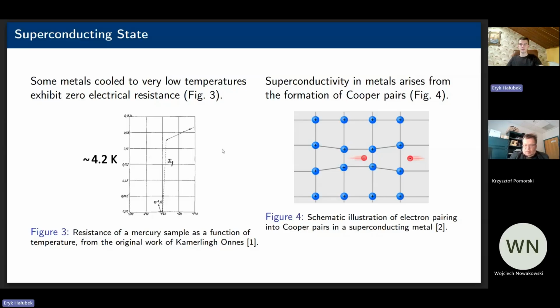So now we know that the critical temperature, which is the temperature at which the mercury changes from a normal state to that state of no resistance, is a little bit lower than 4.2 K. It's about 4.15, something like that.